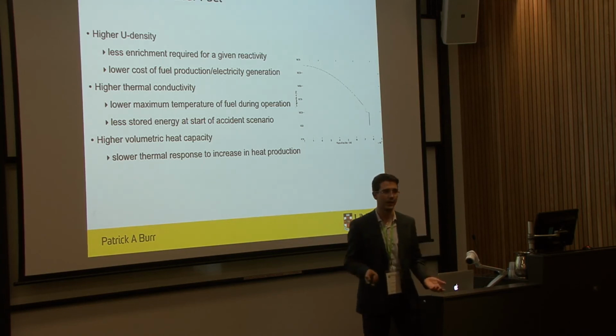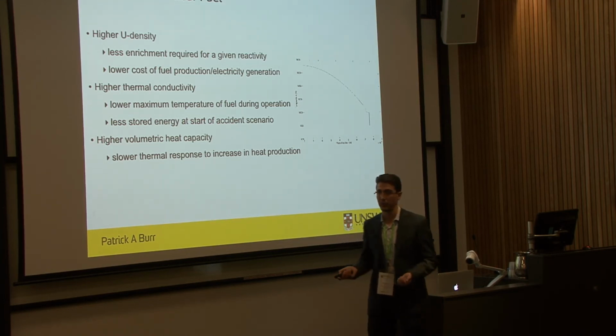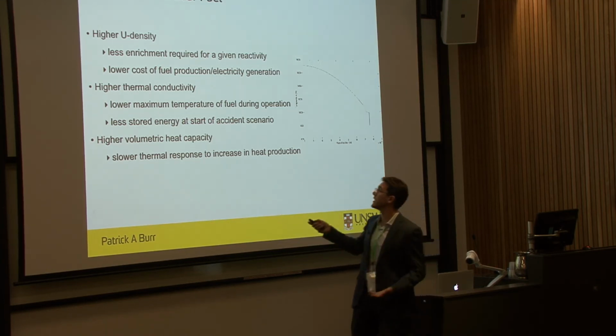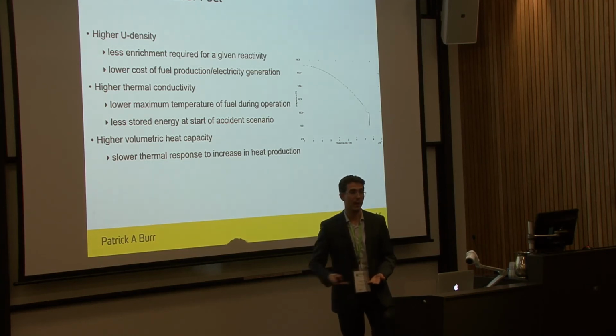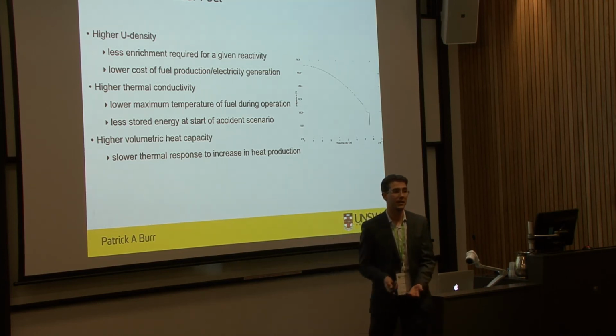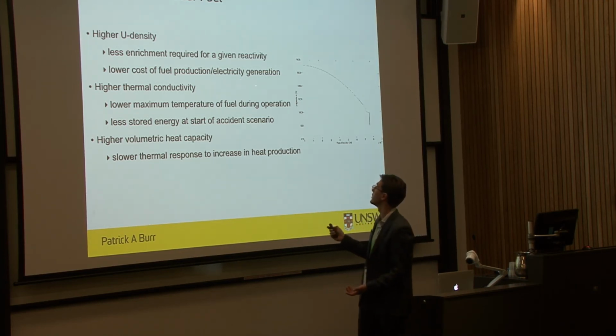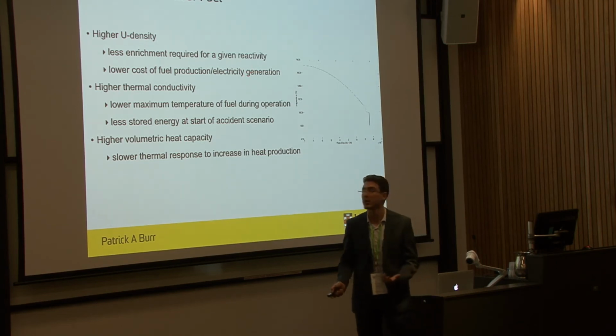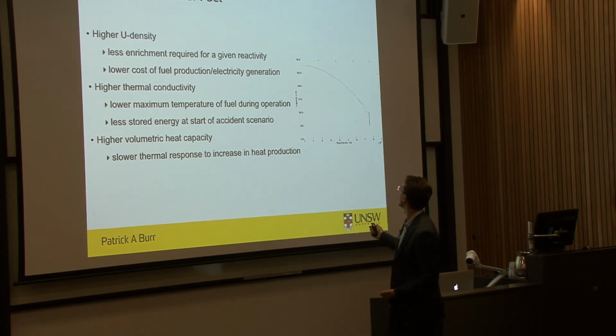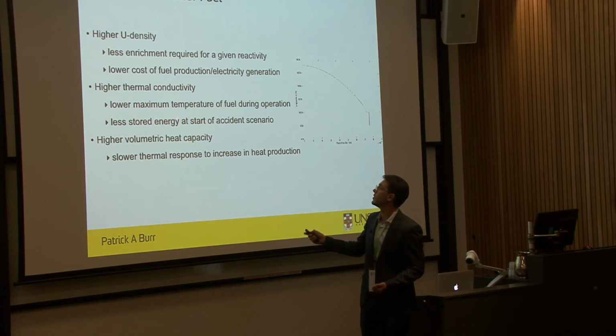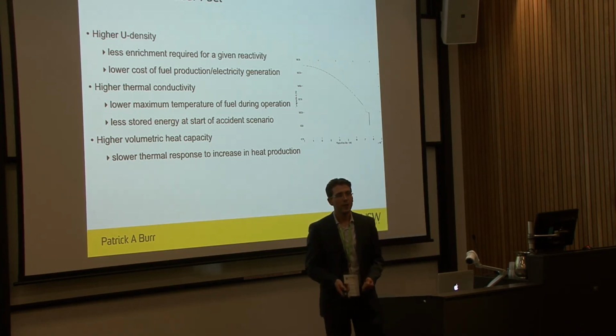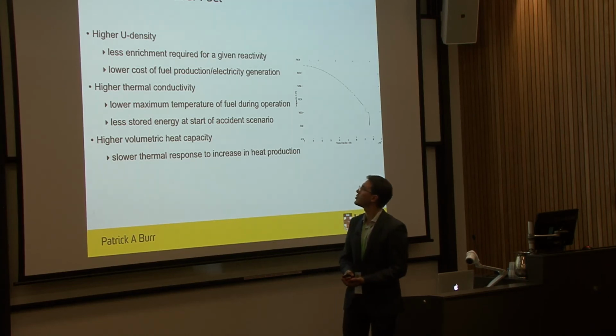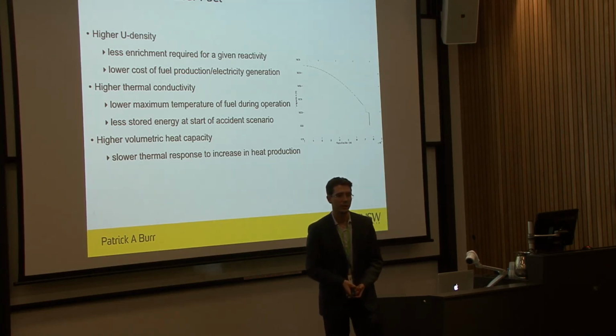And that means saving money on the enrichment. Or the other way of seeing it is you can keep on enriching to the same level by using a high uranium density. Means you can then use a cladding like stainless steel or something that absorbs more neutrons without losing reactivity, therefore without losing money. I apologize, that graph didn't come out very well, but it's about the second point, the thermal conductivity. If you go through the effort of actually changing your fuel, you might try and do more than just increasing the uranium density.